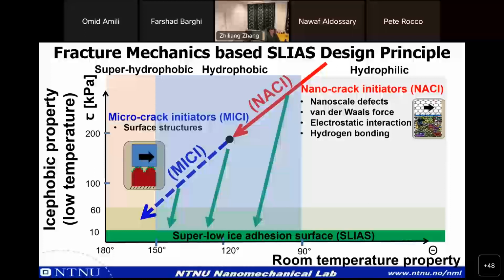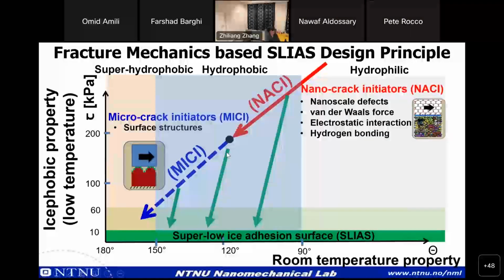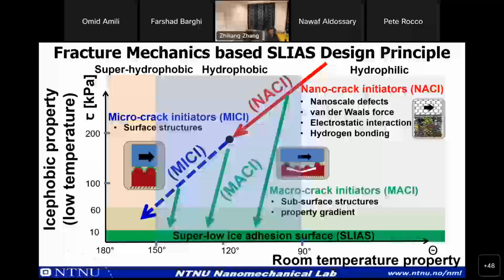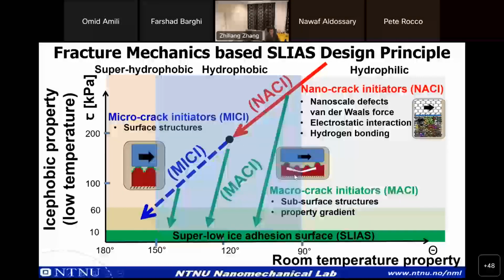The answer is yes. So from here you can see we have done something on the smooth surface. Here we have done something on the surface structures. One thing we have not done yet is the subsurface structures. So we introduce so-called macro crack initiators, MACI. So we can do something about subsurface structures. We can build property gradients vertically. For example, if you have this kind of subsurface structures, when you shear the ice, you will generate cracks at the interface between ice and the surface.